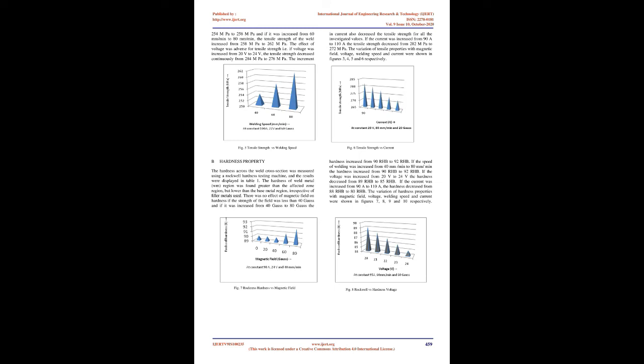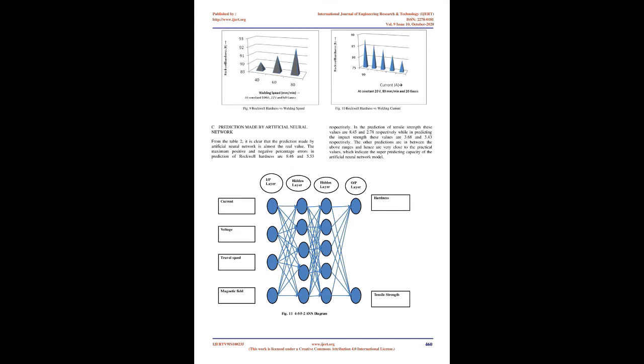B. Hardness property. The hardness across the weld cross-section was measured using a Rockwell hardness testing machine, and the results were displayed in Table 1. The hardness of weld metal, WM, region was found greater than the heat affected zone region, but lower than the base metal region, irrespective of the metals used. There was no effect of magnetic field on hardness if the strength of the field was less than 40 Gauss, and if it was increased from 40 Gauss to 80 Gauss, the hardness increased from 90 RHB to 92 RHB.